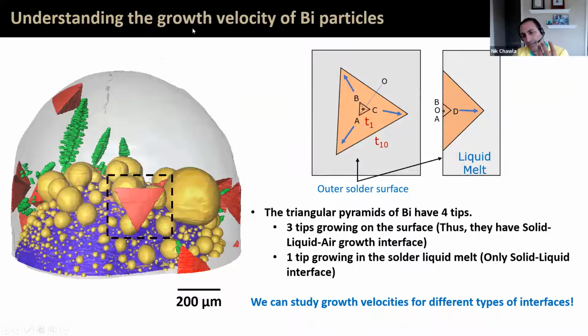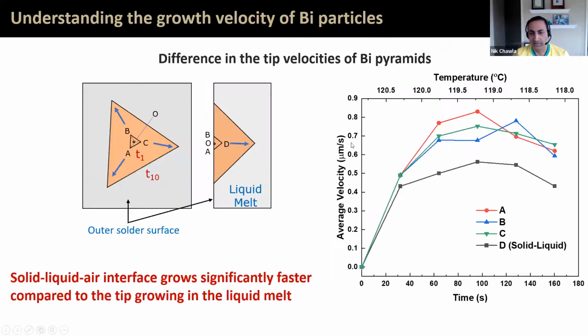So we have actually different time steps for each of these particles. And so you can measure the growth velocity at the tips of the particles. You can also measure the growth velocity at the between the liquid and the solder melt along the edge. Okay, and this is actually some data here.